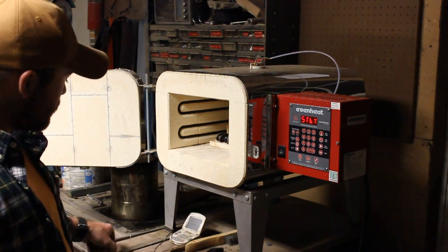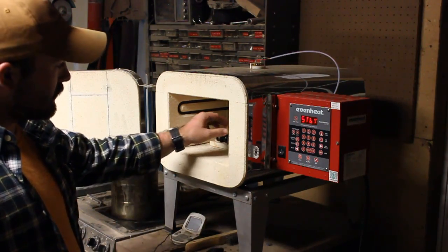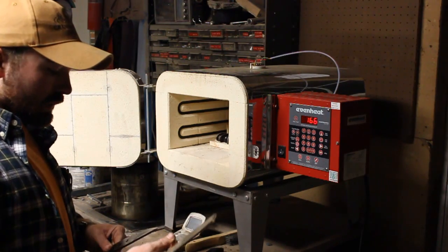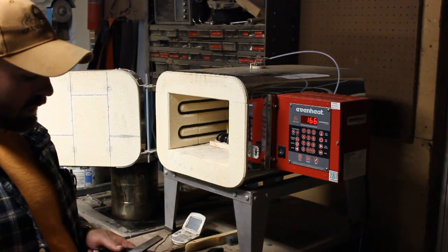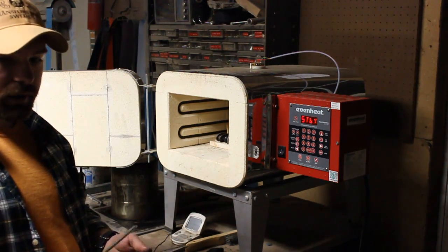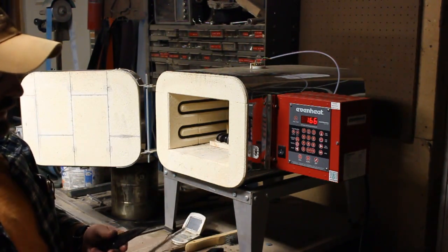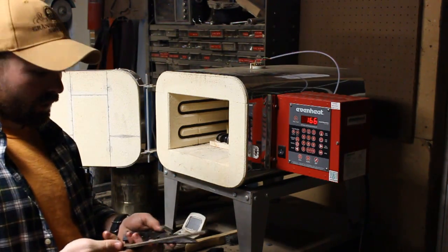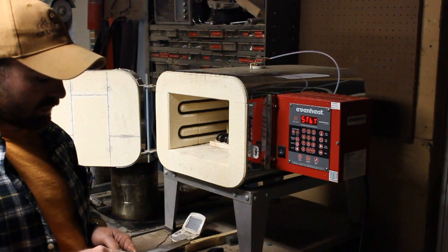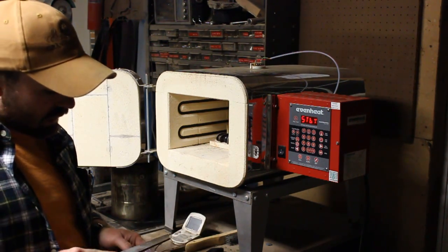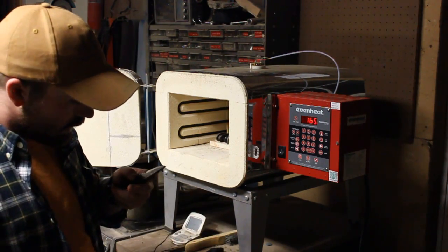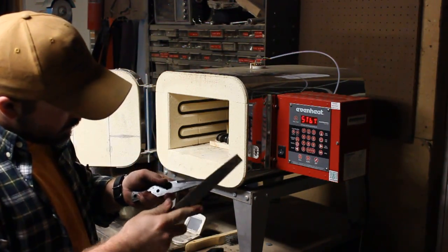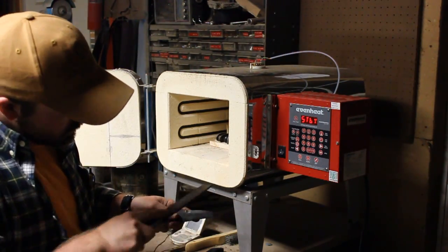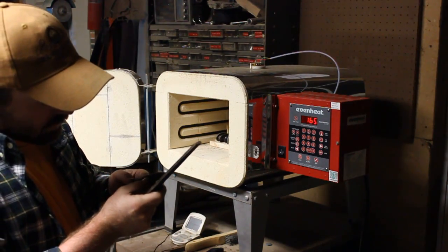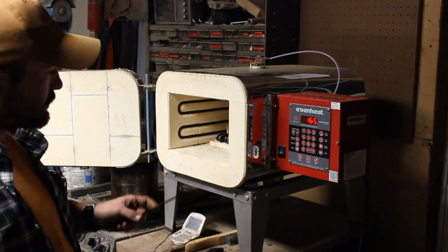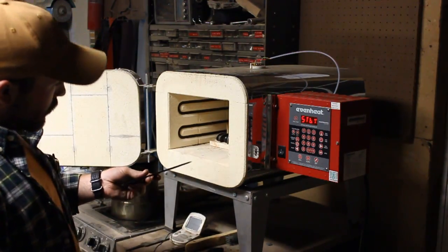One other thing that I didn't mention earlier is, after your knives are quenched, these haven't been tempered yet, these are still freshly quenched blades, testing the hardness. It can be tested with a file. Now be aware that there is some decarb, at least a few thousandths of an inch thick on these blades, so you will get some wear, but you're not going to be grinding into the metal or filing into the metal. It just kind of glides over the steel doing that, and you may not be able to see it from there, but this file's not cutting this knife, this edge, the way that it would if this was still annealed steel. So I know that it's been hardened, and that's what we want.